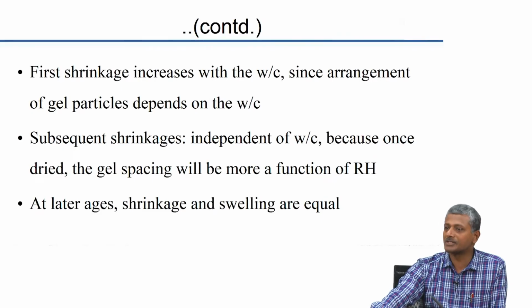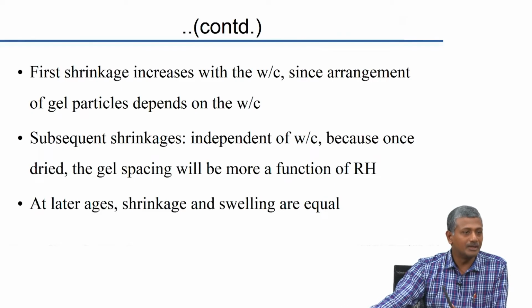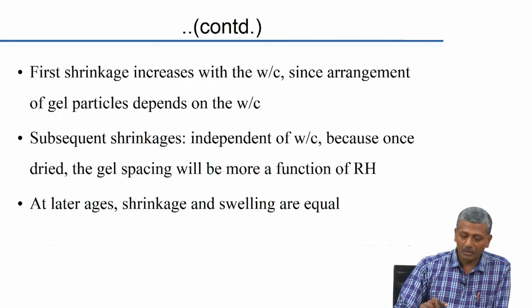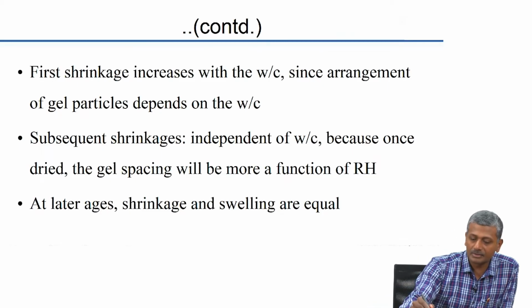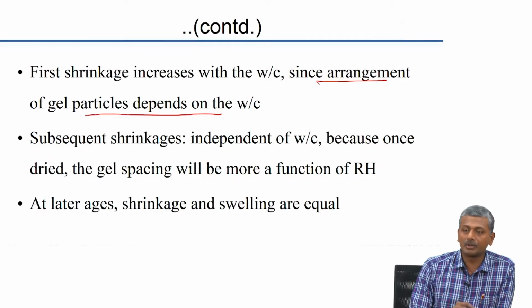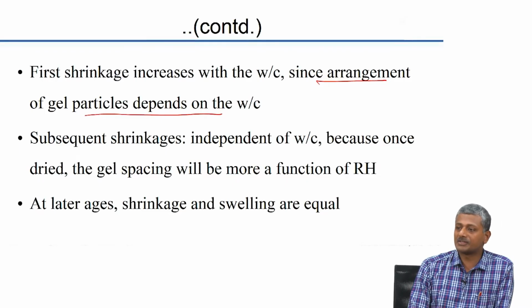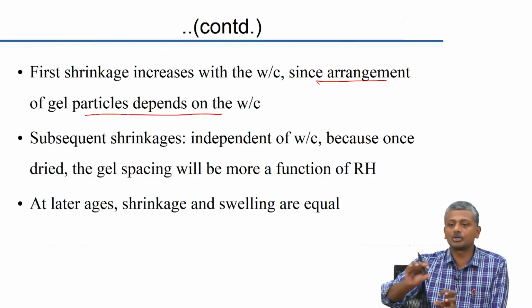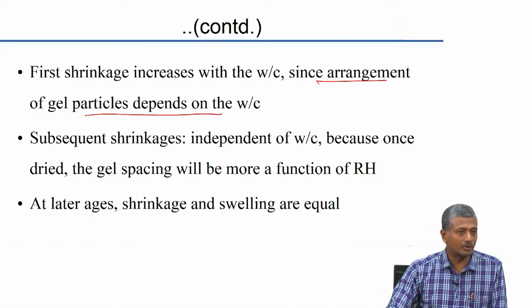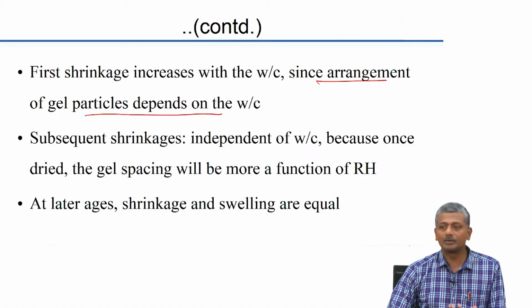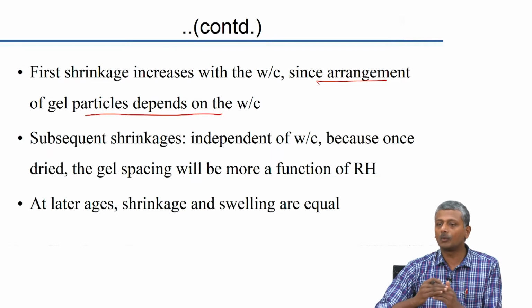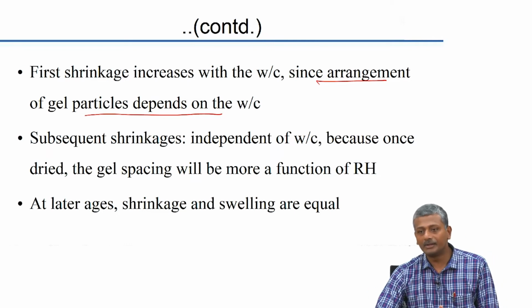Okay. So, first shrinkage, the extent of the first shrinkage increases with the water to cement ratio, and that is quite obvious because there is more water present in the capillary pores, and these are going to get removed, because arrangement of the gel particles depends on the water to cement ratio. Why do I say that? Because your distribution of the extent of capillary porosity and gel porosity depends on the water to cement ratio. The higher the water to cement ratio, the higher will be the drying shrinkage.